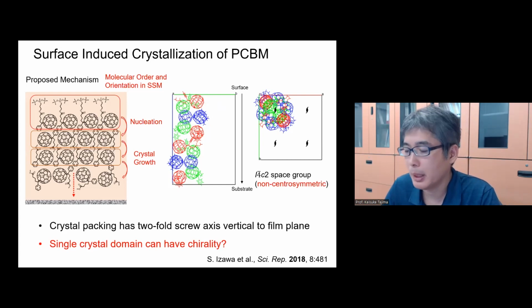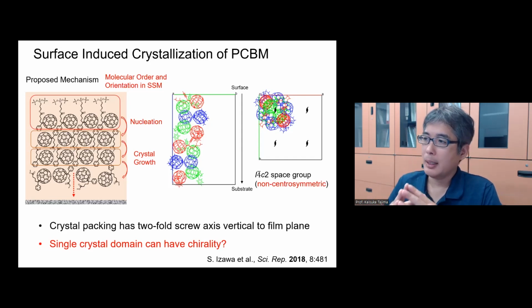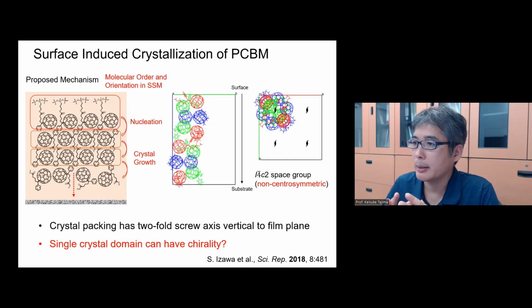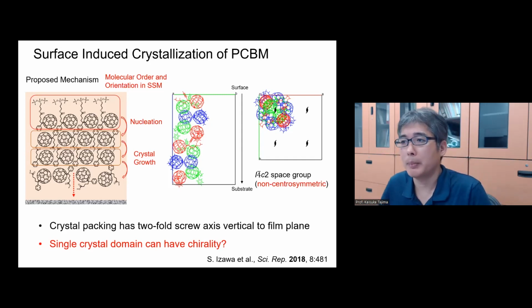it's useless for the amorphous film. Using both spectroscopic ellipsometry and X-ray diffraction, we have very good information by combining these two. Other than that, of course, we can use other spectroscopic techniques like IR, polarized IR, but they often involve difficulty in sample preparation. I would say any kind of optical method with polarizing light would be good to detect the orientation, and X-ray. I couldn't think of any other good or accessible way. That's probably the most popular too.